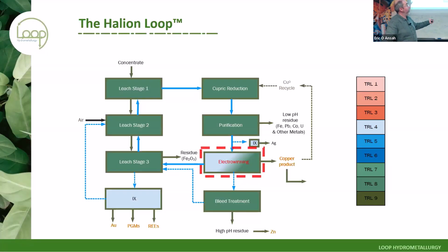Then you need to remove the silver. We do it by IX. Silver is actually the most difficult metal to deal with in this process because the chemistry of silver 1 is very, very similar to the chemistry of copper 1. And so that's the most difficult chemistry in the process. But you end up with a clear 80 gram per litre copper 1 solution.